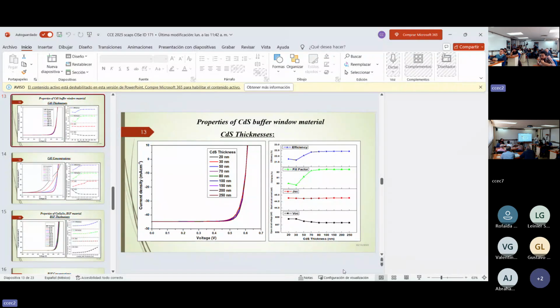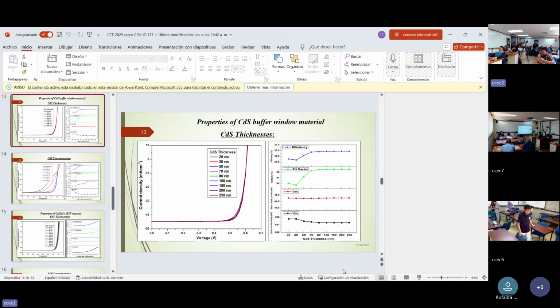And even if you get, it might have some defects in the continuity, or you can say some alternative path for regenerative susceptibility. That was because in this case it is very low, so that might be the reason. I have checked: the shunt resistance is an external parameter for the simulation. It's not a consequence of the... For the simulation, yes. But for the explanation, it might be that at low thickness you might have these defects.